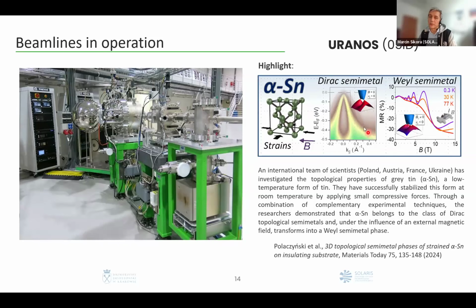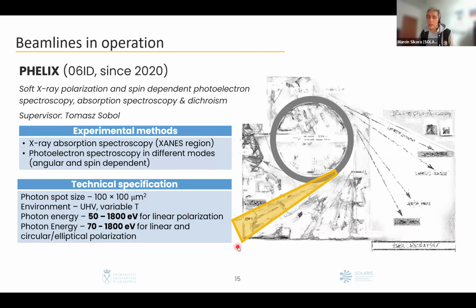but also circular polarization. Another beamline for angle-resolved photoelectron spectroscopy and chemical spectroscopy is the PHELIX, soft X-ray polarization and spin-dependent photoelectron spectroscopy. On that beamline, you can also do absorption spectroscopy because you can use the helical undulator, so you have very different polarizations available, and the beamline is especially good for linear dichroism. It also has recently installed spin filters, but it works in a slightly different energy range. That beamline you can already consider high photon energy excited photoelectron spectroscopy, because here we start from about 50, 70 electron volts, and the useful energy range is up to 1800 electron volts. And the range depends slightly on the polarization that you need.